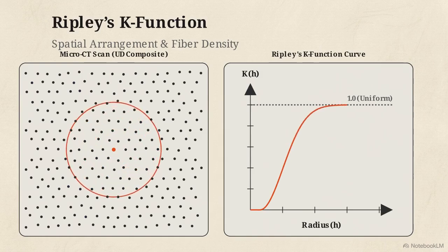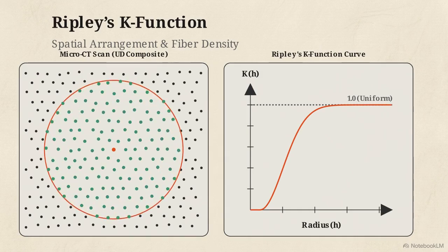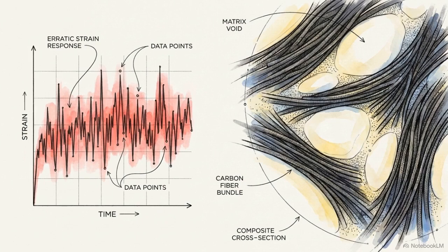In a theoretical defect-free distribution, the resulting curve smoothly plateaus, saturating at 1. In physical samples, fluctuations in the medium range of this curve expose complex, large-scale clustering. These are high-volume fraction defects, completely invisible to basic distance metrics.